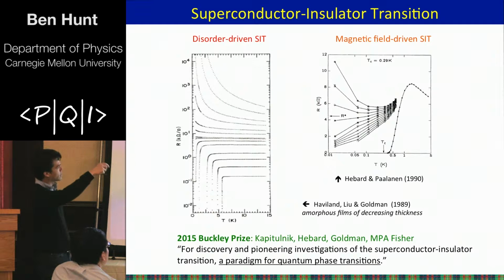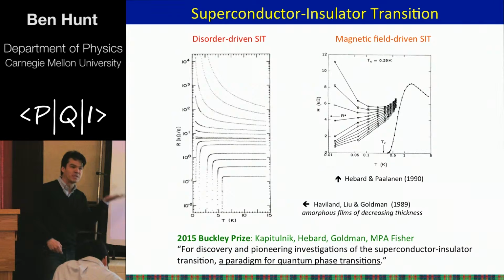So here's a very classic paper from Alan Goldman's group in which they measure the resistance versus temperature of a 2-dimensional metallic film. And they can basically tune from this superconducting transition to the insulator by tuning the disorder, right? And this metallic phase, so some finite resistance at T=0, only prevails for a very, very small range of this sort of phase diagram.